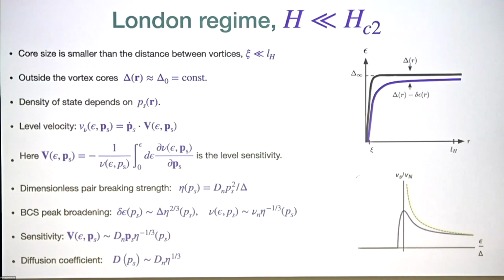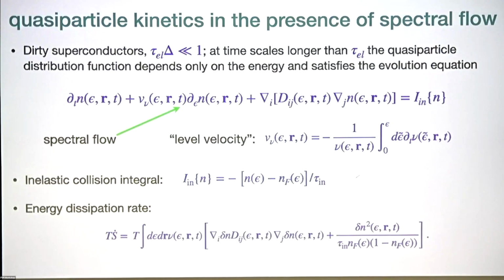Okay, so now let's apply this diffusion equation. So time dependence again, what's the source of time dependence? The source of time dependence is time dependence of the density of states. So basically it's an adiabatic picture where you have a local equilibrium situation where you compute these retarded and advanced Green's functions, the density of states for the quasi-particles. It evolves slowly with time. So therefore you have density of states as a function of energy and time simultaneously. It evolves with time because